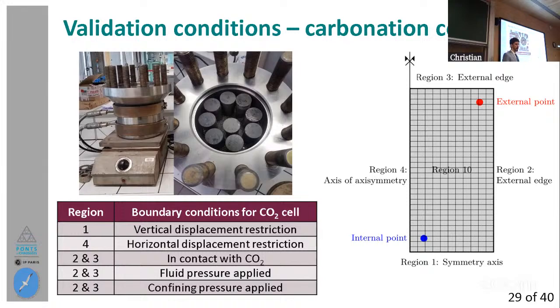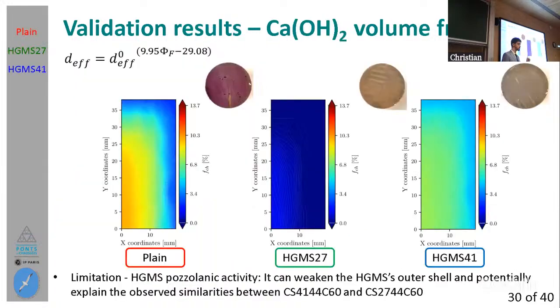With this, I was able to obtain some results, but not before calibrating this important parameter here, which results in the effective diffusivity that we obtained in the model. This effective diffusivity relies on this parameter that I have calibrated for all the samples. I have used the same value of the parameter, and it also accounts for the porosity that we have in the cement paste, on the cement matrix, actually.